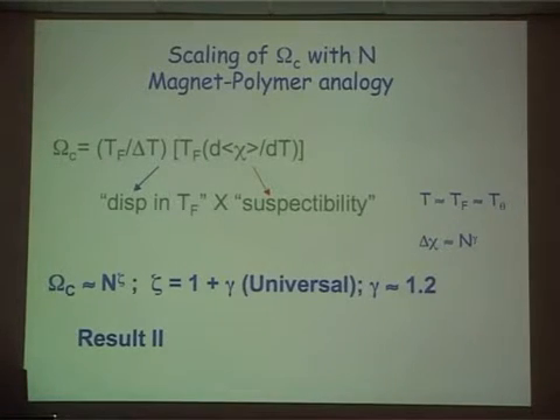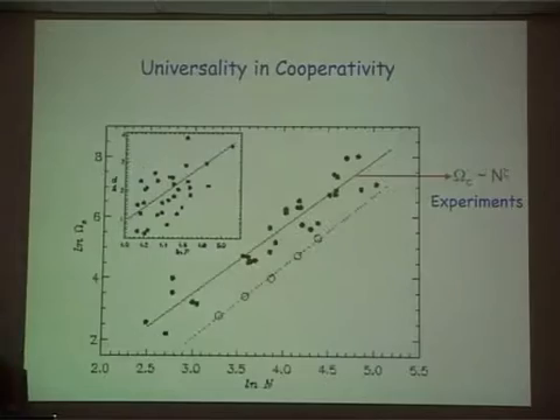Okay, sorry about that. Putting this together, we predict that the dimensionless parameter must go as n to the power of zeta. Zeta is a universal number which is 1 plus gamma. Gamma in 3 dimensions is about 1.2 or so, and therefore you expect this to go as n to the 2.2. This is totally universal. It's an unbelievable thing that when specificity of proteins in fact governs most of its function, we discover a totally universal relation which is independent of various conditions. The question is, is this correct? And of course I won't be telling you if it isn't. This is a log of this parameter as a function of log n, and these are the same proteins for which I showed you delta T over T goes as 1 over n, and here it goes as n to the zeta, and the slope in fact is 2.2.